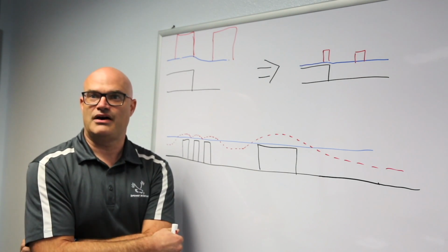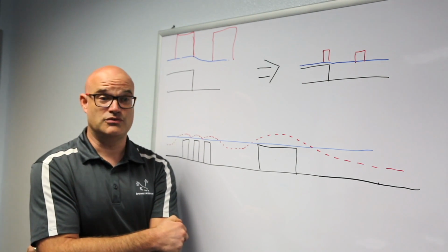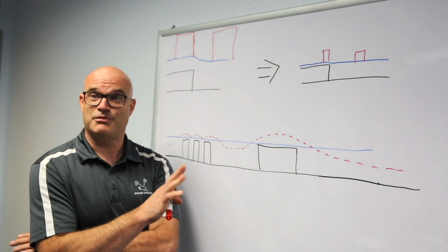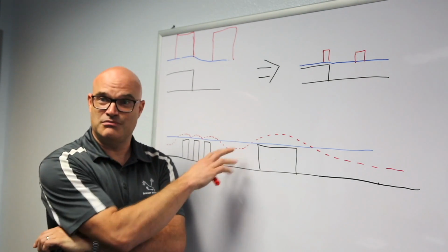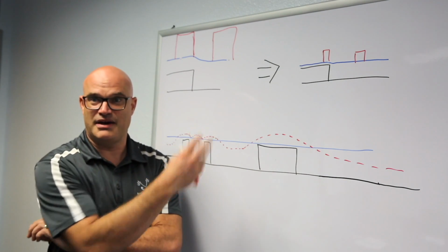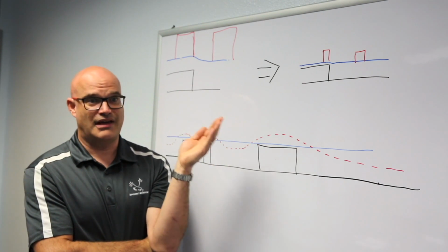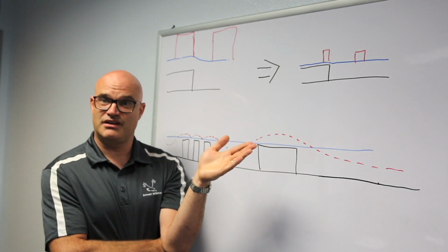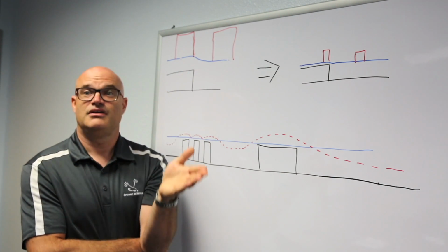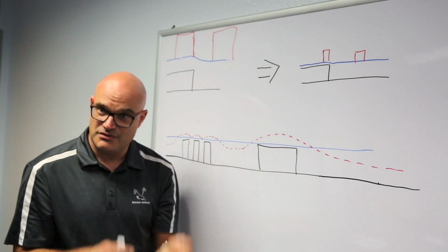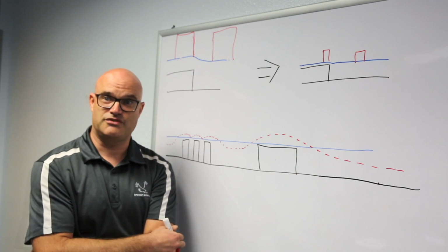You ask how it affects EUV? Yeah, there's other things too. With EUV, magic happens. You don't know why things print better a lot of times. The chemistry underneath the EUV resist has an impact on how the EUV resist works. Because honestly, we're going to be pushing our hard masks down to 10 nanometers thick, with a resist that's maybe 30 nanometers thick. So it's got to etch transfer. So then all your other stuff has to have the etch budget, and has to be small enough or thin enough to be able to transfer that.